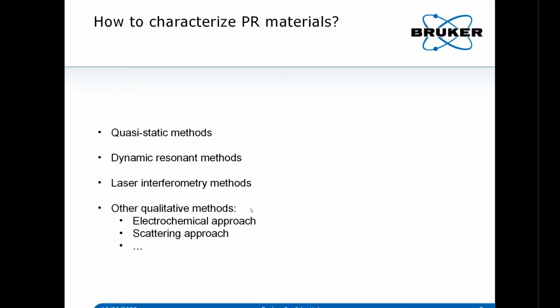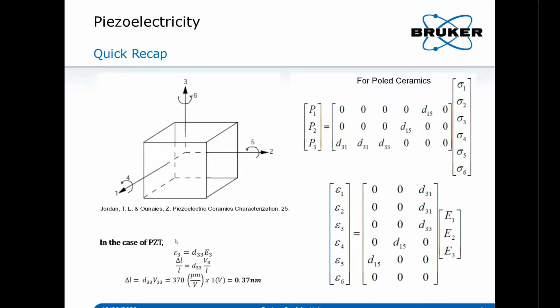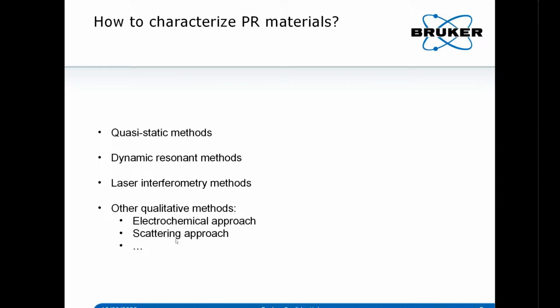So in the traditional way to characterize the piezoelectric response, as Dr. Chang mentioned earlier, we can just press the material and measure the voltage change. But again, when it comes to thin films, this kind of response can be quite small. So the traditional quasi-static method can sometimes be very difficult to carry out. And of course, we can also use the dynamic resonance method. In the previous equation, we see that your D33 is related to the dielectric coefficient of the material. So by using an impedance meter or things like that, we can use the dynamic resonance method to measure the dielectric material, and from there, we get the piezoelectric coefficient.